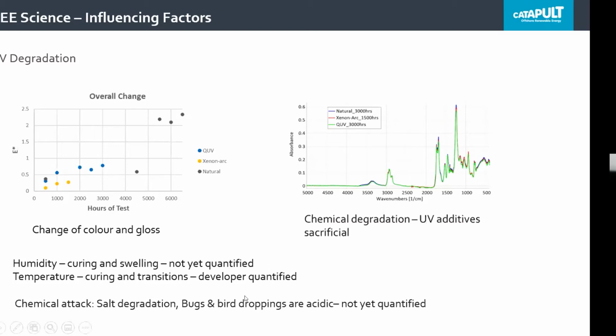Other things to consider are the humidity. Particularly in terms of polyurethane systems, which a lot of rain erosion materials are, if you're curing it in situ on a wind turbine blade under high humidity, the resultant material might be different to what you achieved and rain erosion tested in the laboratory. Temperature is usually pretty well known in terms of Tg transitions and quantified by the developer. Other areas that still need to be investigated are that the coatings or product solutions could be under degradation from salt, and also acidic degradation from bugs and bird droppings, and that information has not yet been quantified.